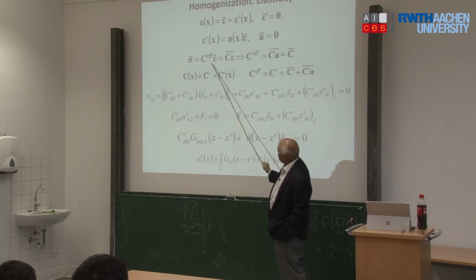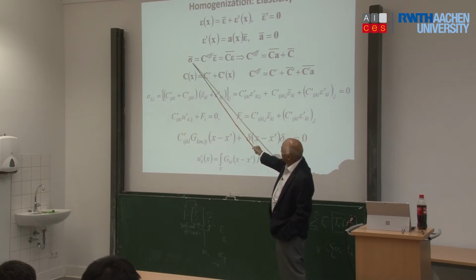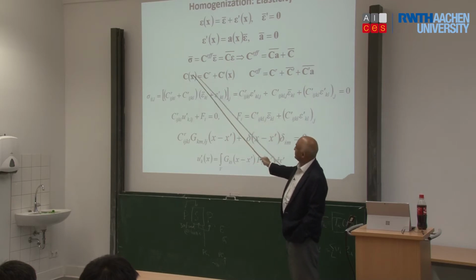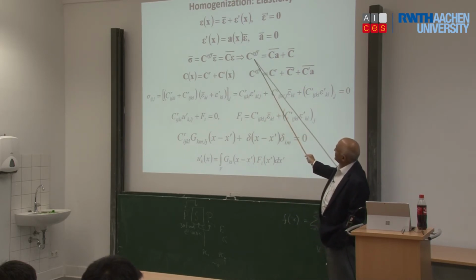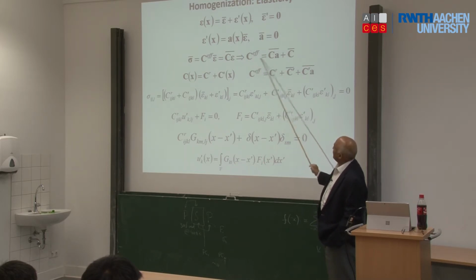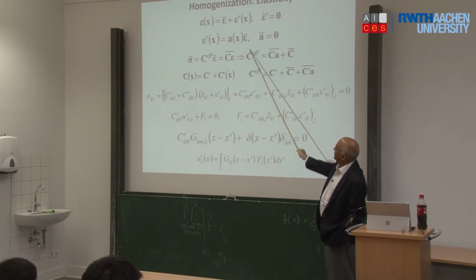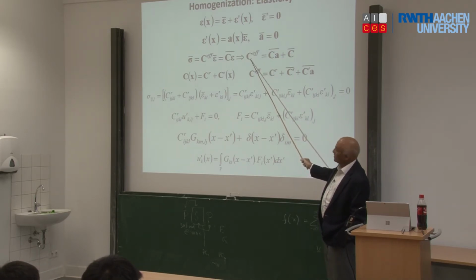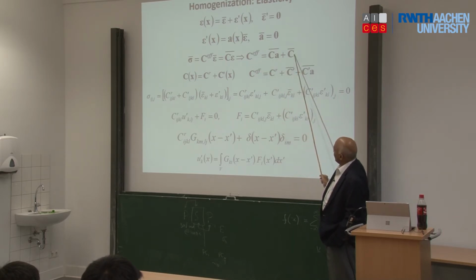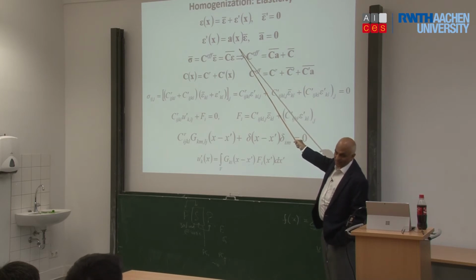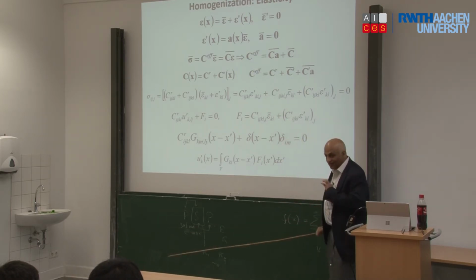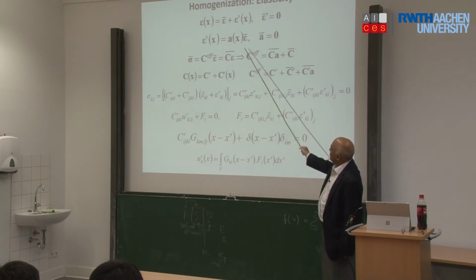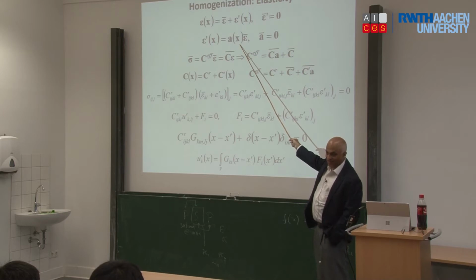We already said that this came from the last slide, right? This is what I started as a homogenization theory thing. But of course, the average stress is nothing but the average of the stresses. So if I equate these two and use that idea, then it turns out C effective is nothing but C bar plus C times A, this one. The nice thing about this is you can see it no longer depends on what you impose as strain, right? So now I have an equation for C effective simply as a function of the C at each location and this localization tensor. So the effective value can be rigorously solved if I know how to get the localization tensor. That's the only problem standing in our way, right?